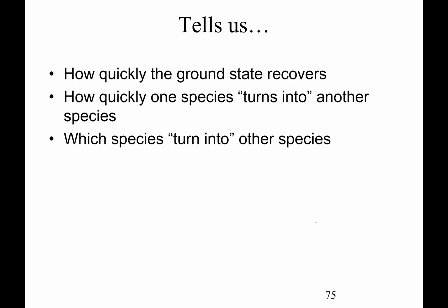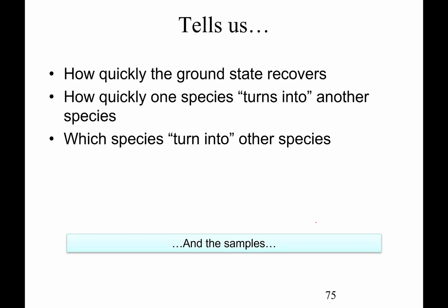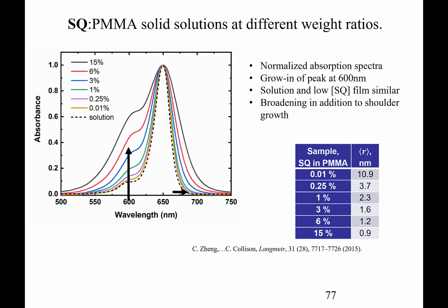So let's look at the samples. So here's what we have. We have a certain sample of squaraine within a certain amount of polymethyl methacrylate. We dope from 0.01%, very low concentration, up to a pretty high concentration of 15%. This data is very similar to data that was published in 2015. This data I'm showing you today is also published in 2019.